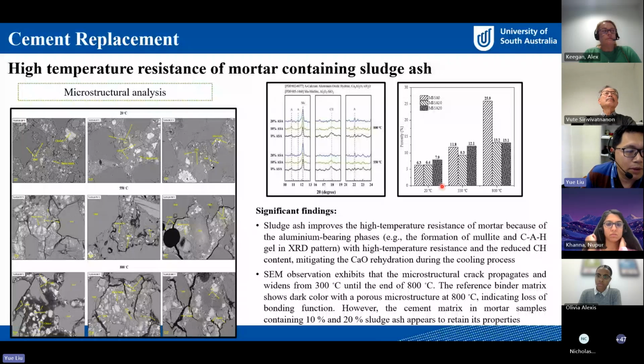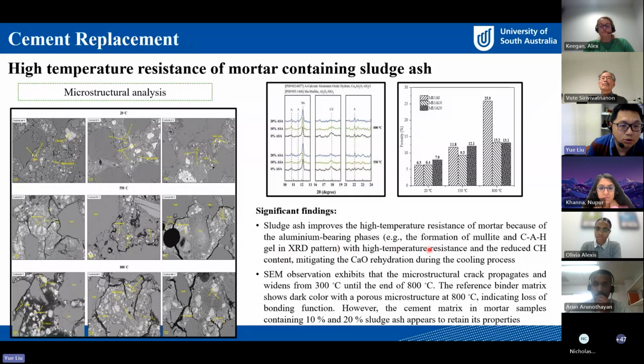After the chemical and microstructure analysis, we found the improved high temperature resistance is mainly from two aspects. First is the formation of some aluminum-bearing phases, like the formation of mullite and calcium aluminate phases with high temperature resistance. Also, because the pozzolanic reaction of sludge consumed some calcium hydroxide. Calcium hydroxide will decompose after heating to between 400 and 500 degrees, producing calcium oxide.